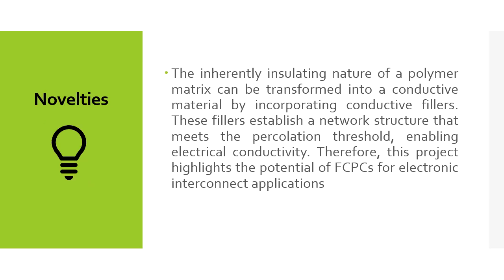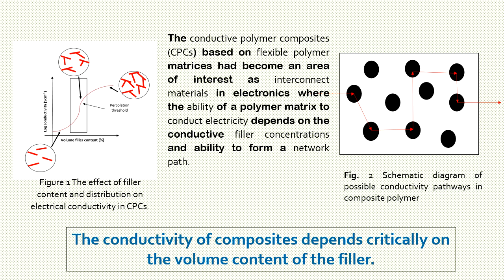The novelty of this invention basically lies within the insulating nature of a polymeric material, whereby we transform it into a conductive material by incorporation of conductive fillers. These conductive fillers establish a network structure that meets the percolation threshold, enabling electrical conductivity. Therefore, this project highlights the potential of FCPCs for electronic interconnect applications. Basically, for flexible conductive polymer composite, the conductivity of the composite depends critically on the volume content of the filler itself.